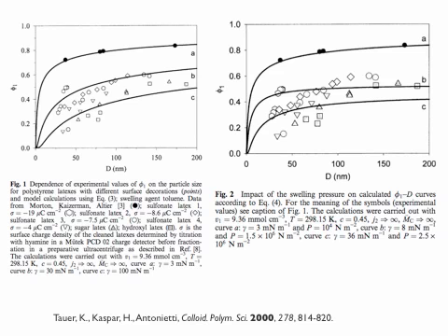Now, we talked a little bit about what if this latex is less charged? If it's less charged, it would mean the surface tension is higher. So the second and third sets of data have a lower surface charge density, minus 8.6 microcoulomb per square centimeter and minus 7.5 microcoulomb per square centimeter. And you can clearly see you can swell less. The reason for that is that the interfacial tension is higher. So you take up less monomer in that particular case.